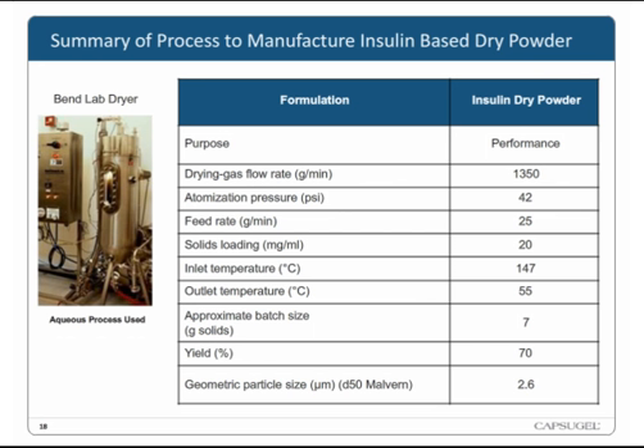And so that outlet temperature was much, much lower than the glass transition temperature of the product we were making, which means that we wouldn't have issues with sticking of the product, but also that the dry powder was essentially frozen and not mobile, meaning that we felt confident that that would hold the insulin in place at elevated temperatures and not allow for any sort of chemical degradation or unfolding.